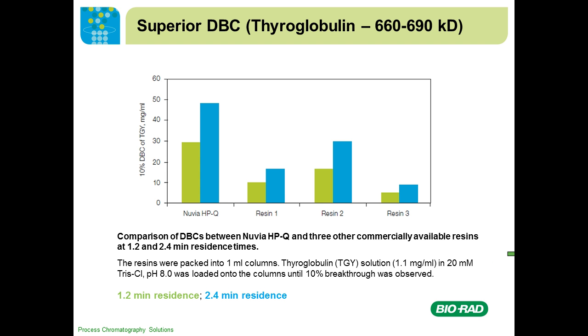We also compare the binding capacity for large biomolecules. For example, thyroglobulin has a very large molecular weight, and we compare chromatography resins available in the market for biomolecule purification. Some of them are dextran-based, some polystyrene-based, and some methacrylate-based. As you can see, Nuvia HPQ has the best binding capacity. We tested different residence times, 1.2 minutes and 2.4 minutes. In every case, Nuvia HPQ has the highest binding capacity.